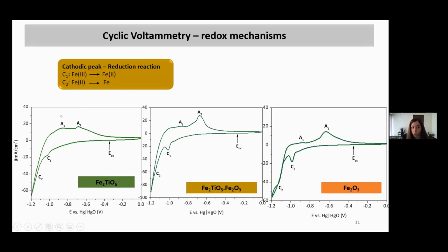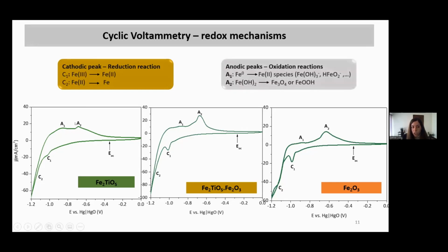On the other side of the plot, we have two anodic peaks, which are associated with oxidation reactions. So the first one, we have oxidation from iron 0 to iron 2 species, and the second, iron 2 species to iron 3 species.